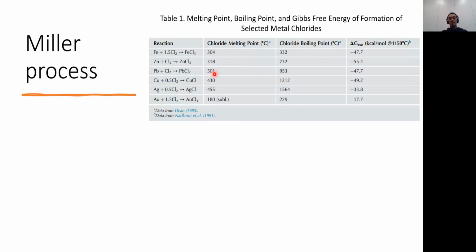A little bit about the Miller process. So Doré bullion, once it's melted and then added with chlorine gas, is at some melting point, and this gives the free energy of selected metal chlorides that usually exist in the gold bullion. As we can see from the Gibbs energy, all of the materials except gold will form these chlorides. So gold will be safe there in the metal melt, but all the chlorides will form slags, which are further processed to recover the silver.